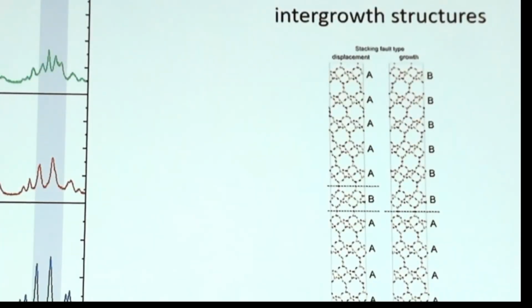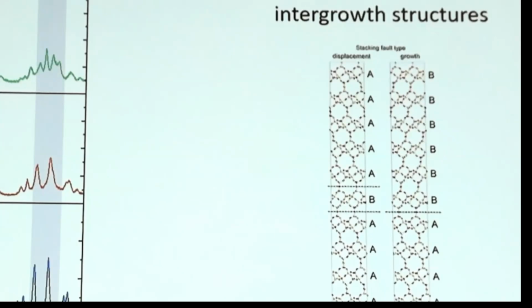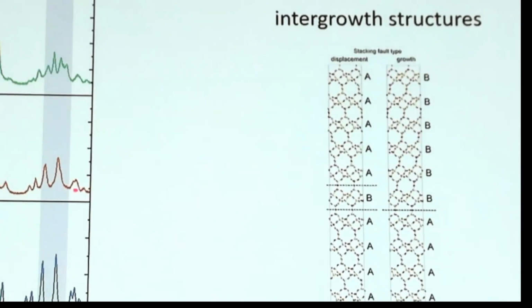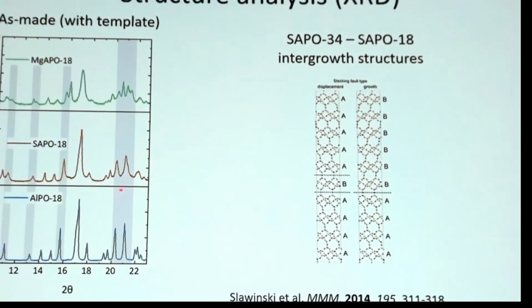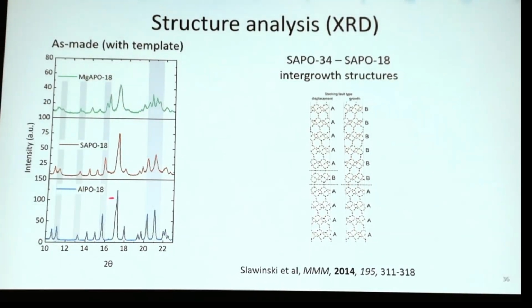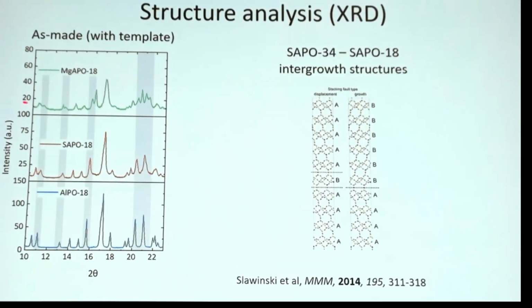Now, this is of course interesting, and it is interesting to find the reason why. And we went to structural analysis to elucidate this. What we can see here from XRD is that this is a perfect AlPO-18, so AEI structure. Then in the silicon material, we see that some peaks here are lower than they were in the other material. And when we come to the magnesium material, we see that there's something going on here, and especially here, and also here.